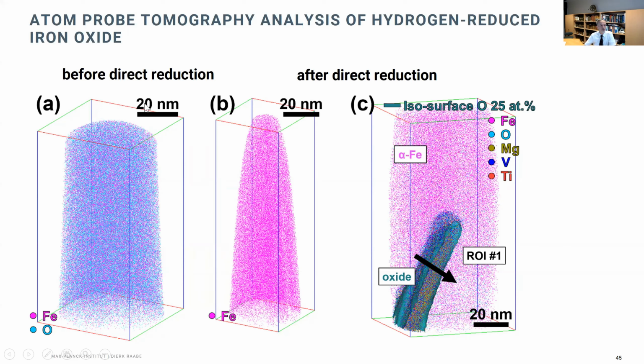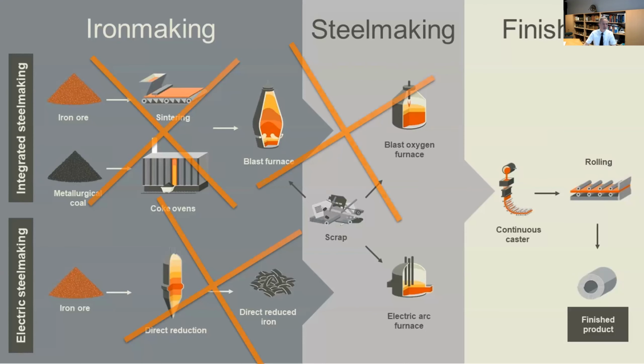Here you see it before the reduction. Very unexciting. You just see these dots of iron oxide. Everything is fine as it is. And after the reduction, you see the pure iron. But what they discovered is that you have all kinds of very fine nano oxides that seem to remain in the material and don't get removed, don't get reduced. And that for sure also has an influence on the overall kinetics.